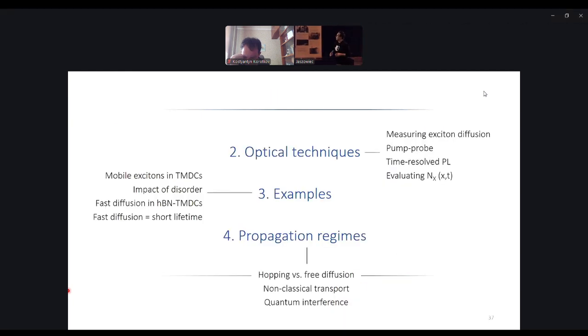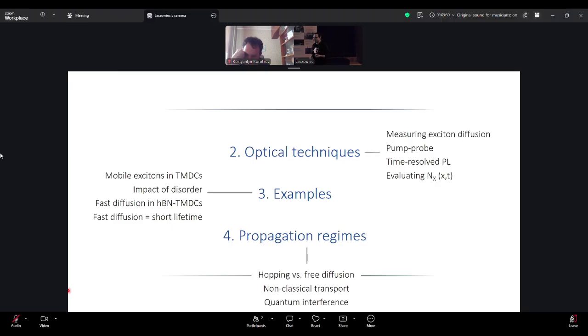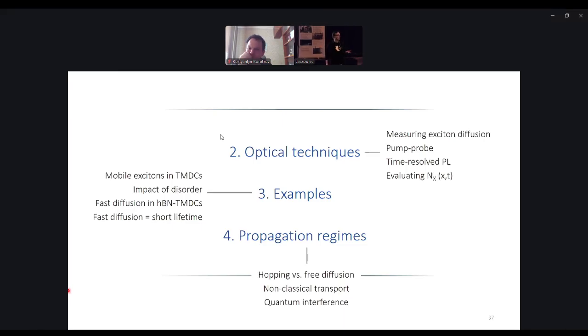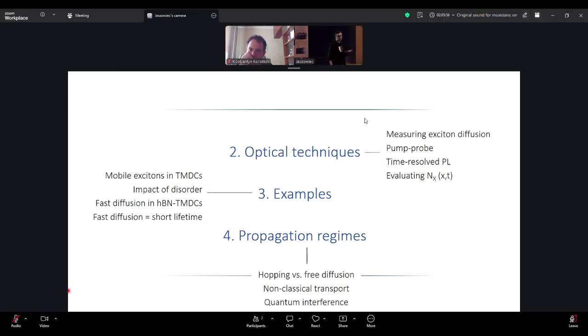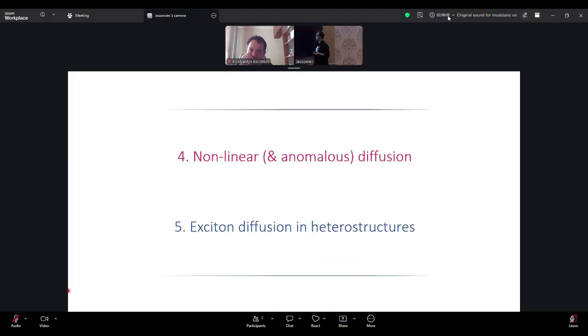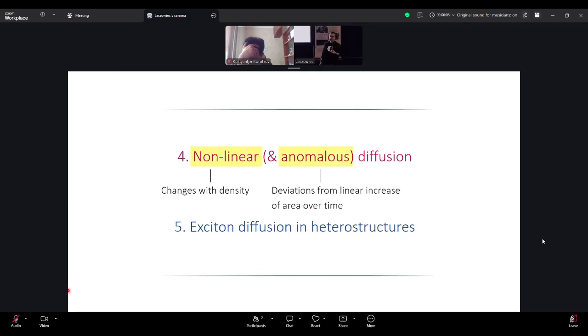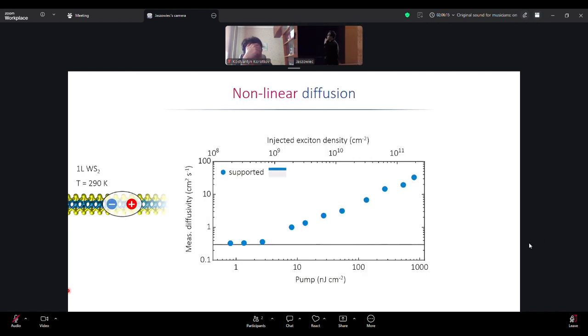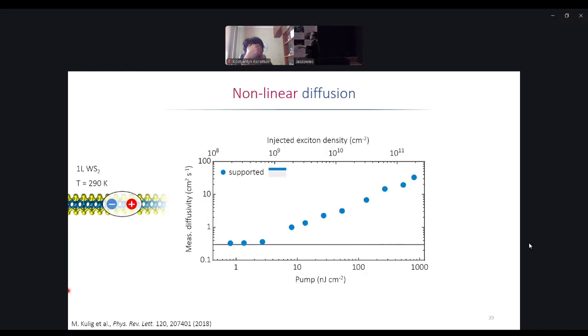And with this, we're done with this part, all in the linear regime in terms of exciton density. However, what can happen very quickly in experiment, for everybody who's doing optics in particular, you can always pump it harder, and sometimes even pumping gently already brings you into the nonlinear range, and the diffusion can become nonlinear, which means it changes with density, and also anomalous, which means a deviation of this linear increase of area over time can occur. And one example is a very simple system, definitely subject to disorder.